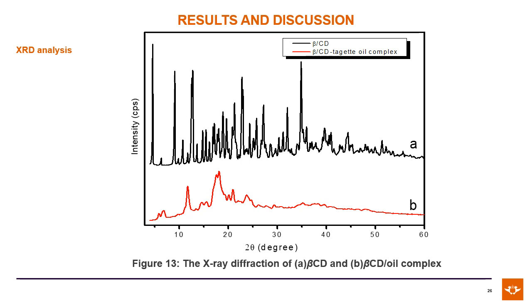The XRD pattern of beta-cyclodextrin showed intense sharp peaks that indicate the crystalline nature of the compound. On the other hand, the XRD pattern of the inclusion complex revealed a greatly reduced crystallinity in the complex system, as evidenced by fewer and broader peaks of lower intensity.